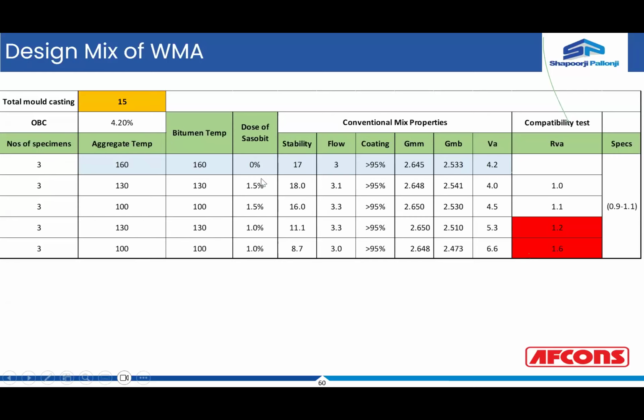Now the idea is when you change the doses of the additives, what will be the effect on the stability, flow, coating, GMM, GMB, VA, and what is the ratio we are getting. So if you see the top three combinations, wherein you can see the aggregate temperature is 160 degrees. The first one is the hot mix asphalt, which is giving you a VA of 4.2. This is the controlled condition.